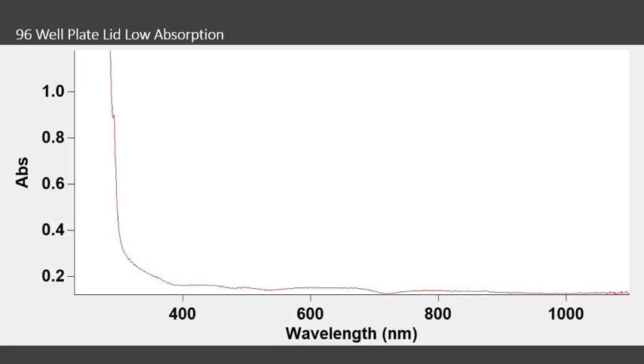So we ran it through the UV vis, and we see here at around 808, it's very, very low absorption, and so we were not worried about the lid interfering with that experiment.